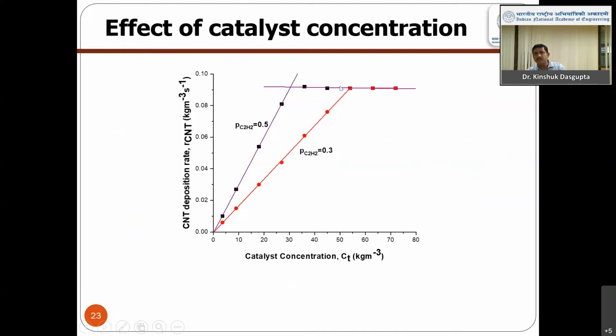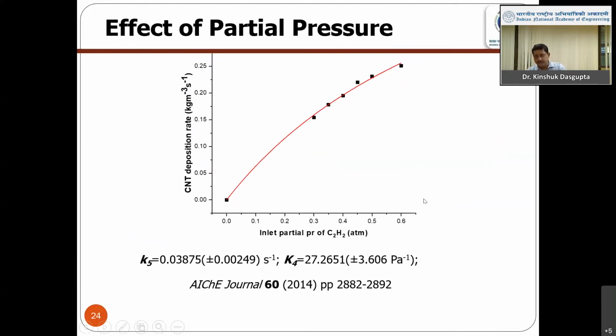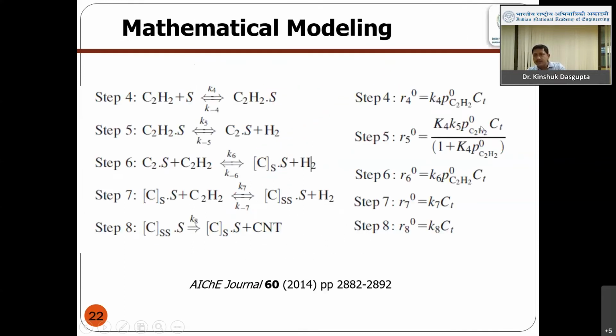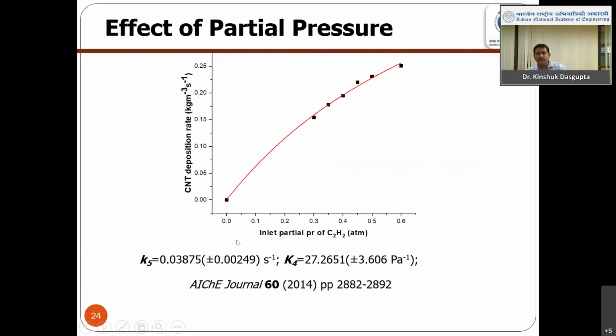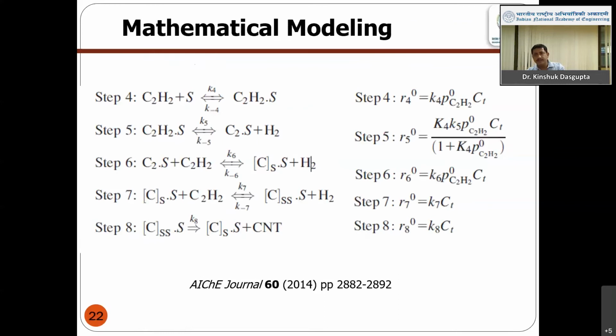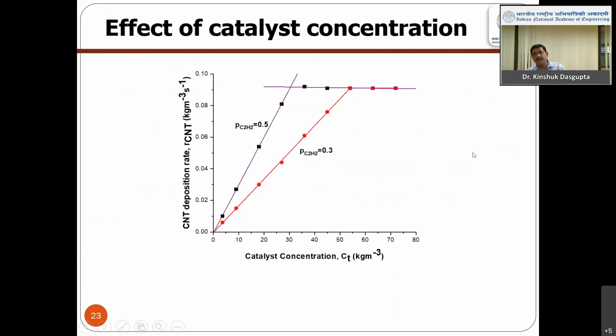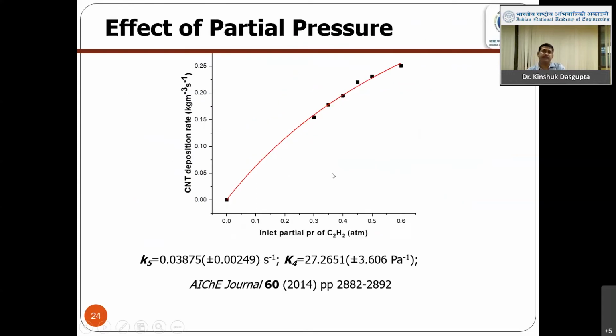Obviously, they reach some saturation value where it is constant. And if we look at the partial pressure, it varies differently for different steps. So we plotted this data and tried to fit it with different equations, and we could see that the fifth step, that means this equation, could be properly fitted to the data. So then we can say, okay, this is the rate controlling step.